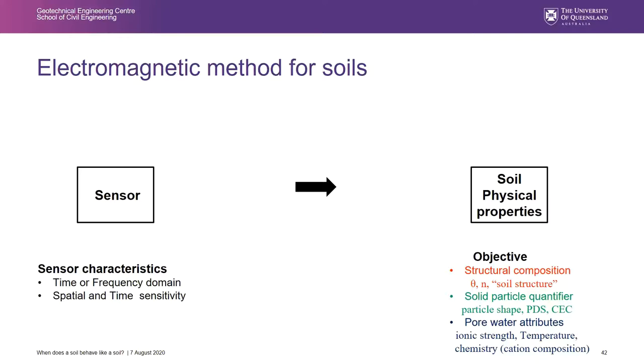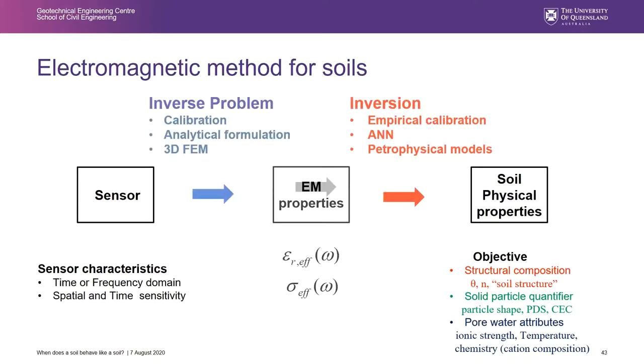And then you will have the pore water attributes, which is basically the conductivity of water, the mineralogy of pore water, everything like that. So the way to measure it, basically, Alex, can you move to the next slide? Basically it's a two-step process. The first step is to use a classic inverse problem to extract the electromagnetic properties. So depending on the frequency range, you might want to talk about effective permittivity or effective conductivity. And then there is an important step of inversion to extract the soil properties from these measured electromagnetic properties.